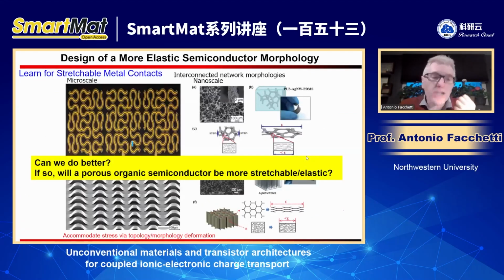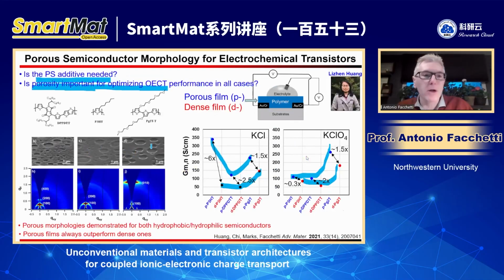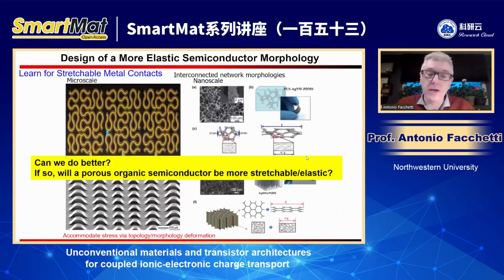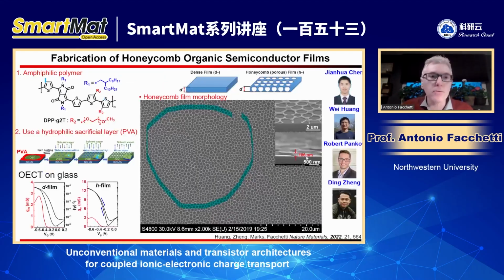However, the question remains, can we actually do better? These are not really good morphology without polystyrene. You see, they are not really a very nice interconnected network. It's just rather random porosity. And this is something we have done more recently. This is an SEM image of a semiconductor, this polymer, without any polystyrene, in breath figure.